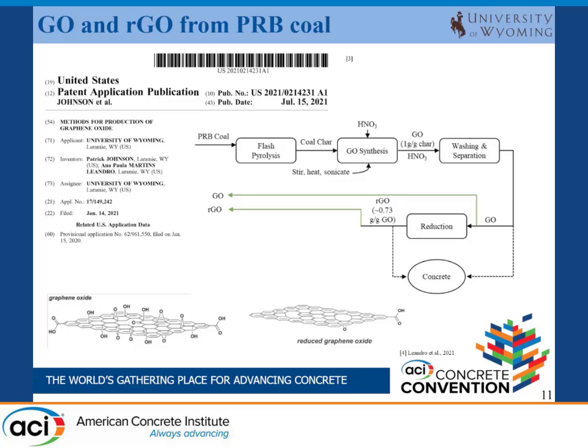We extract that graphene oxide by bypassing the Hummers method or the modified Hummers method that is normally used in the whole world. We are using a different oxidizing agent, nitric acid, to extract the graphene oxide. In some analysis, we found that from 1 gram of char, we can get approximately 1 gram of graphene oxide. And from that 1 gram of graphene oxide, by eliminating the other impurities, we can get 0.73 gram of reduced graphene oxide. That means the byproduct of the graphene oxide is very less than the other method.